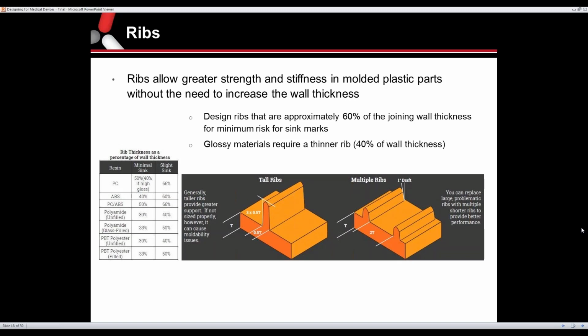A lot of times, consideration is needed for the strength and stiffness of the parts, the application. You want to incorporate gusset ribs, rib structure. We have a small chart to the left here with different materials and the sink rates. You definitely want to maintain a certain height of rib versus the width versus the wall stock. As you can see on the two right areas there, that's just showing some basic ratios that you want to follow as a rule of thumb when you're designing your parts.